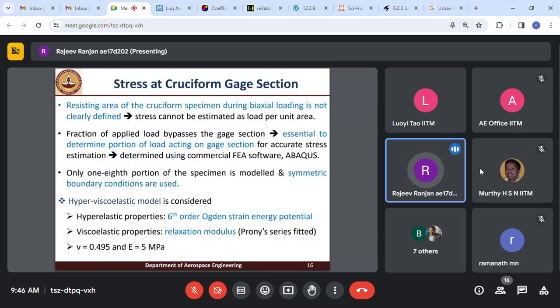Since in the cruciform specimen there is no clear resisting area, stress cannot be estimated directly as load per unit area. In order to calculate the stress, the fraction of applied load which bypasses the gauge section needs to be determined. To do that, we used the FE software Abaqus. Since the geometry and loading were symmetric, only a 1/8 portion of the specimen is modeled, and symmetric boundary conditions were used along with the hyperviscoelastic model. A hyperviscoelastic model was considered for this FE analysis.